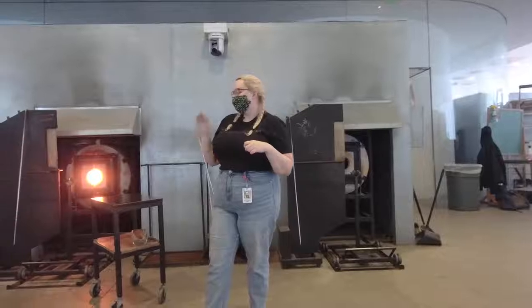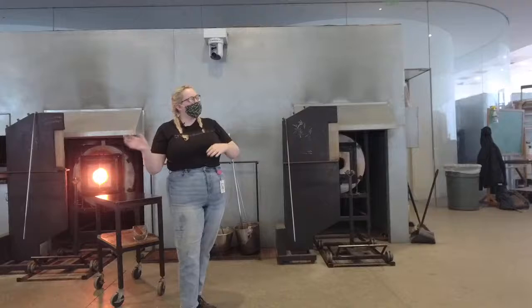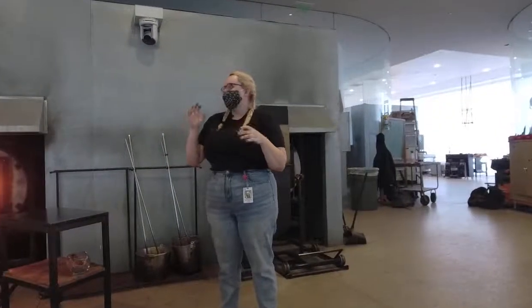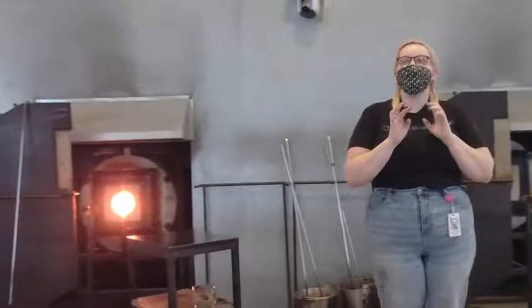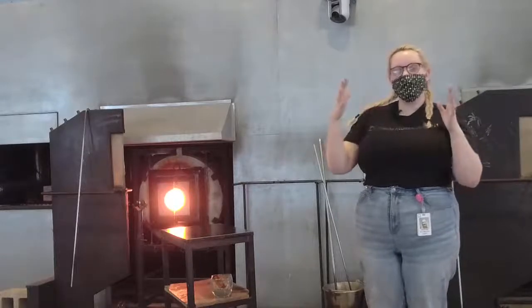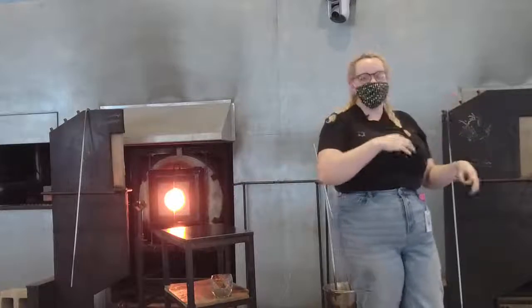If we were to take this glass — and you can really see the color now; I don't think it's really yellow, I think it's sort of an orange situation — if it had made it and not ended up on the floor, we would load it into our annealing ovens. When glass is hot, we can't really let it cool down in the air because the air is too cold — it causes it to crack and break really easily. So we cool it down slowly. If you come and visit, the museum is open Wednesday through Sunday. We have a really large bench in our ancient gallery, and that bench annealed for about 11 months and still has tiny bubbles and cracks, meaning it really needed to anneal for about six more months. If you guys have any questions, comment them below. Thank you guys so much for watching — we have a backlog of tons of other demos, and thank you for joining us.